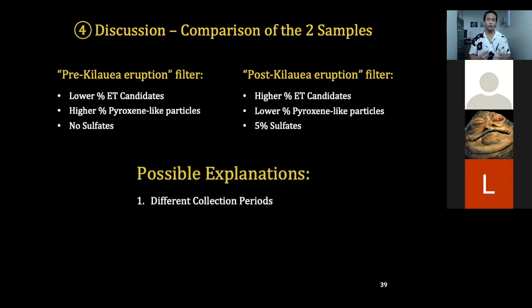Number one, obviously we collected them in two different collection periods, approximately 2 years apart, so different types of elements were just arriving in our samples, or in our sampler. Number two, these two filters were exposed for a different number of hours. And just as a reminder, the post-Kilauea eruption filter was exposed for over twice as long as the pre-Kilauea eruption filter. During this time, there may have been an extra meteor shower that could have possibly explained the spike in the percentage of ET candidates in the post-Kilauea eruption filter.